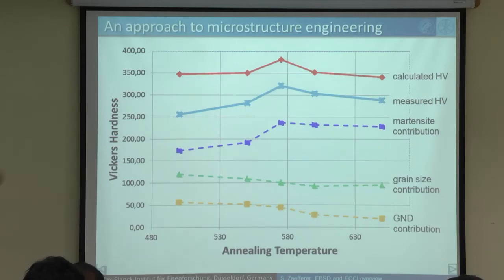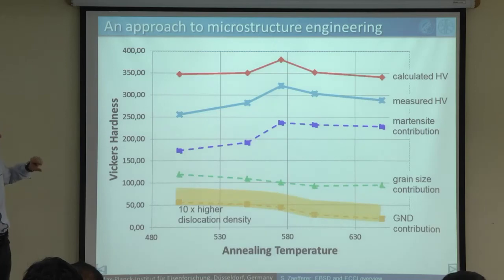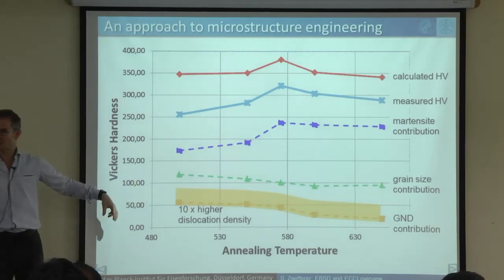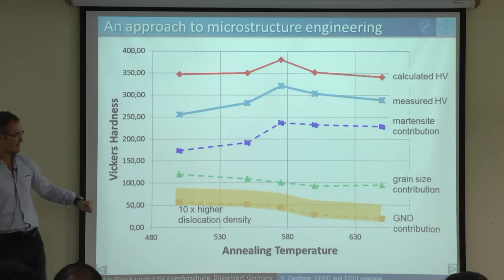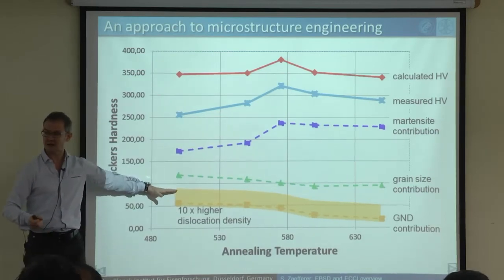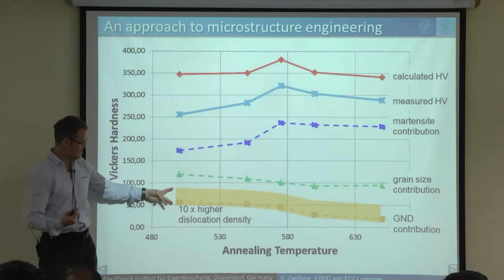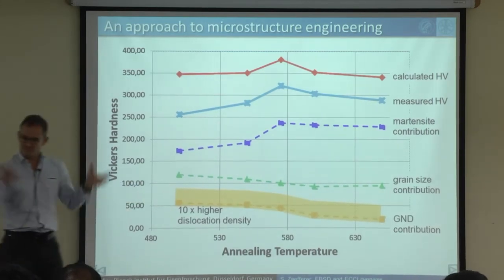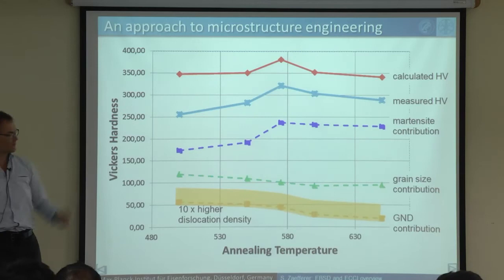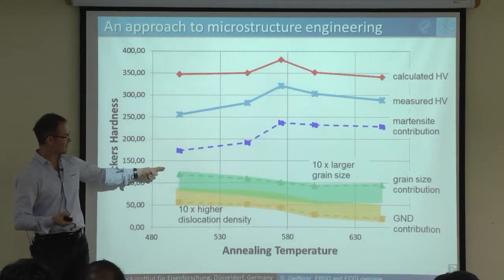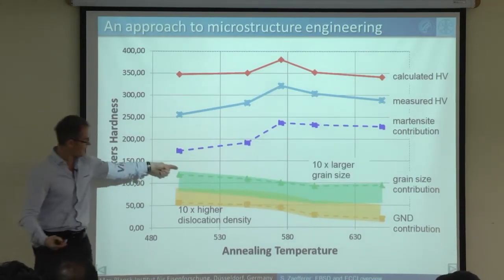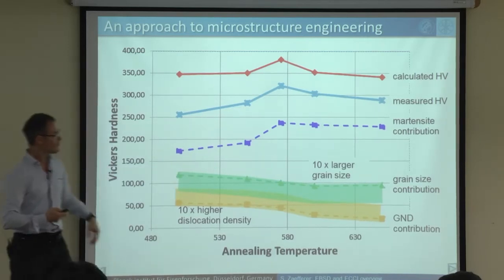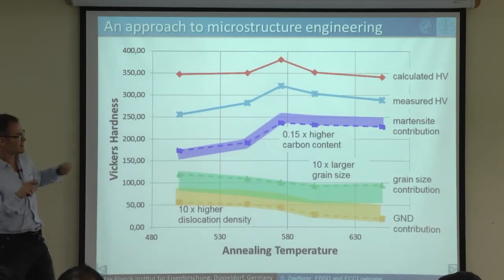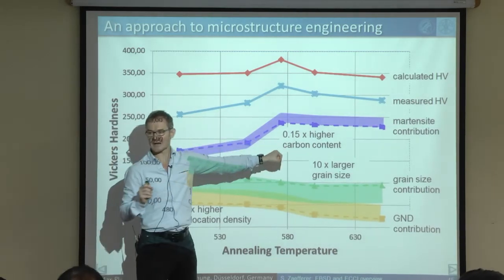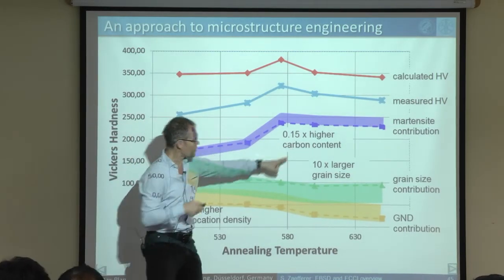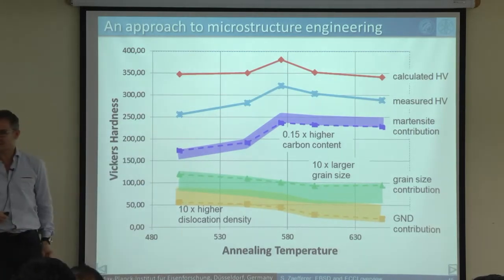And now you could say, okay, what would happen if I change the martensite volume fraction a little bit? Oh, start with GNDs. If I would change the dislocation density by a factor of 10, then we would get up to this place here. The hardness would rise up. And we can say 10 times makes this change. For an engineer, fantastic to know how much is the effect of it. How much would it be if I make the grains larger, or smaller? If I make them larger, the hardness would drop by that. What would happen if I change the martensite content? I only make 15% more martensite, and I get a surprising increase of strength.